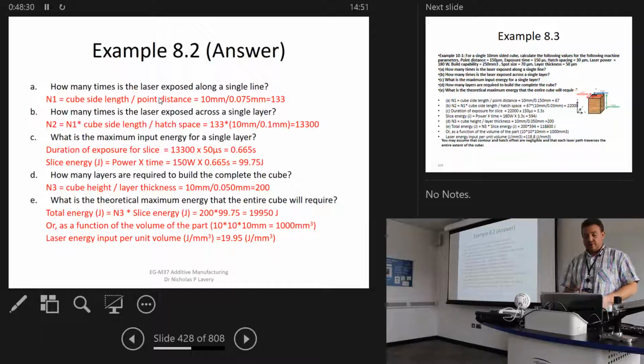If we assume that the energy going into the slice is power times time, we've set the power at 150 watts, and we've got the time, 0.665 seconds, that means we need 99.75 joules going into that single slice. Now, each slice will have to repeat every 50 microns throughout the whole build, so we can work out there are theoretically 200 layers to do the 10 millimeter build height. So the total energy that goes into that cube is N3 times the single slice energy: 200 times 99.75 joules is 19,950 joules.